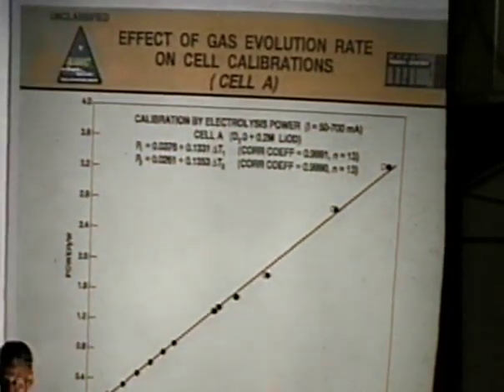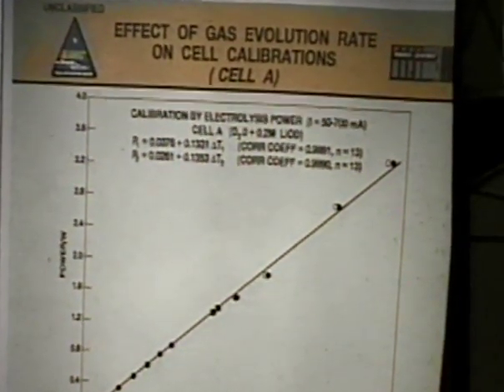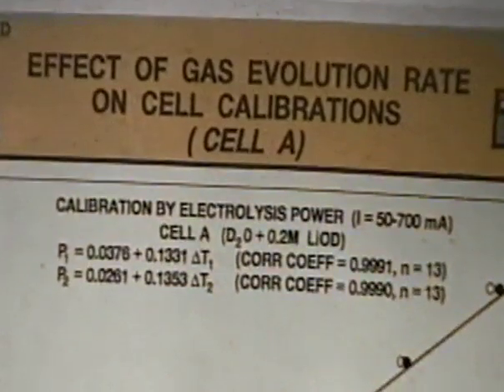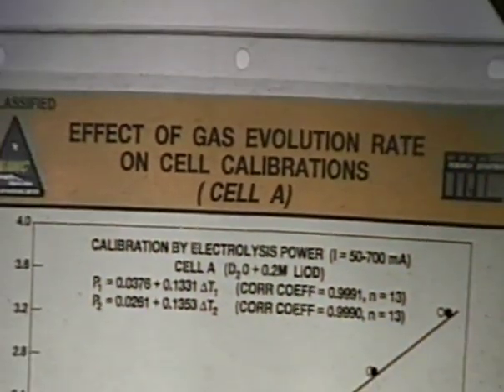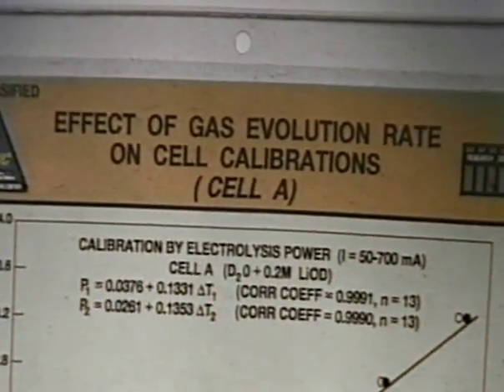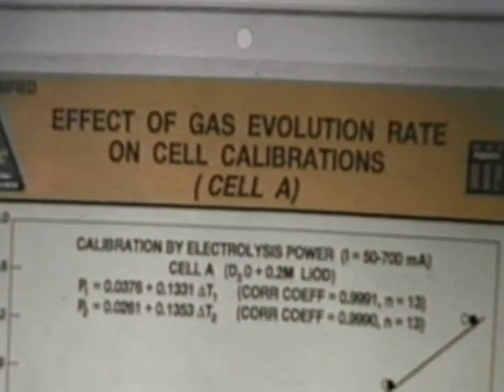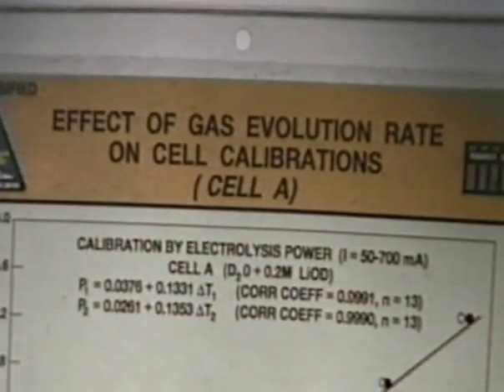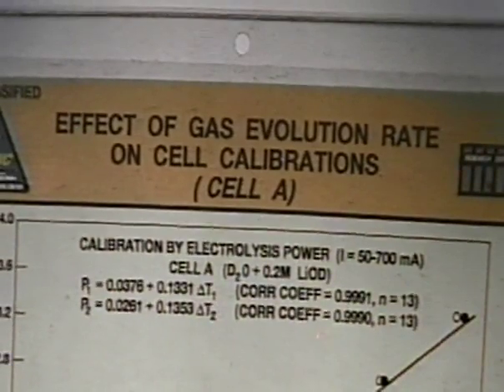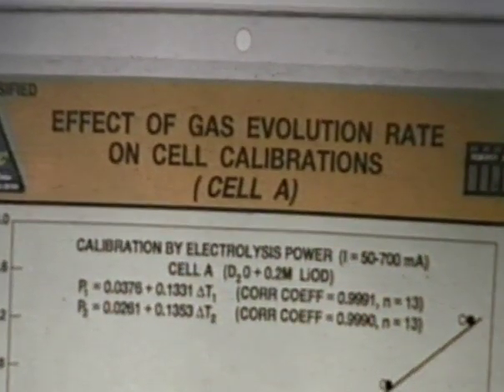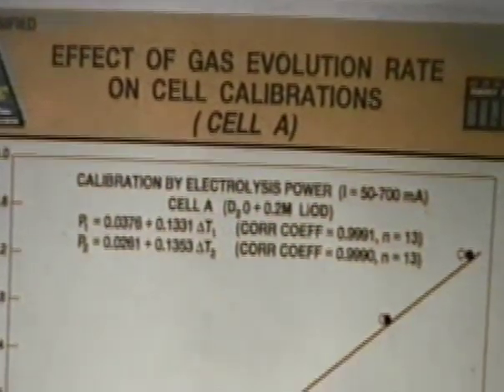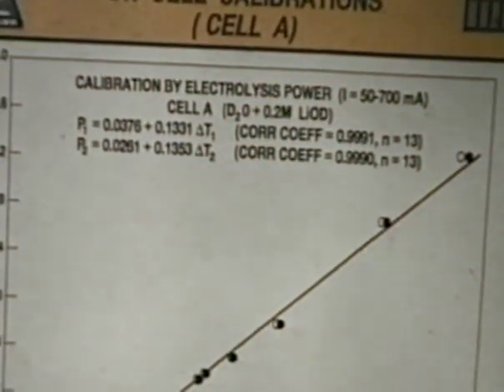And we've calibrated this many times, both by electrolysis, the power we put in, the delta T we get, temperature from inside the cell to the water bath, and we get a good correlation. Correlation coefficients are always 3 nines or better, and we've also calibrated by resistor heating, joule heating, and we get similar results with that calibration.